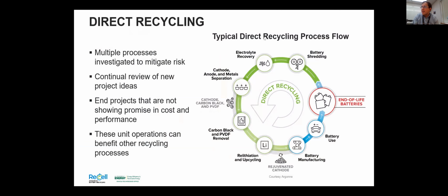So direct recycling. This is kind of the process for recycling using this direct method. A lot of the other processes are similar in that you first do some sort of reduction step. You either shred the battery or you do what's called hammer milling to break the materials down into smaller sizes. You then have to do something with the electrolyte. People do different things. There's thermal processing, they basically just dry off all the electrolyte. There's people doing some organic or biological decomposition of the electrolyte. For direct recycling, we're basically planning to actually recycle the electrolyte, and I'll talk a little bit about that.